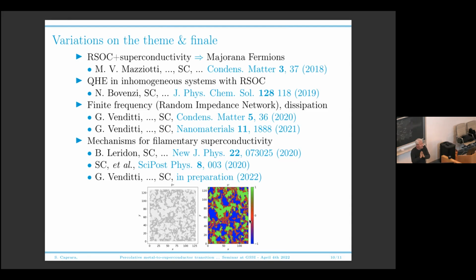You have a topologically protected filamentary superconductivity that sneaks between two different domains of the charge density wave order parameter. And they have to be, because you cannot possibly go from up spin to down spin without passing through the XY plane. And so this is topologically protected. This is very robust against disorder. And as a side product, you have a very, very filamentary superconductivity.